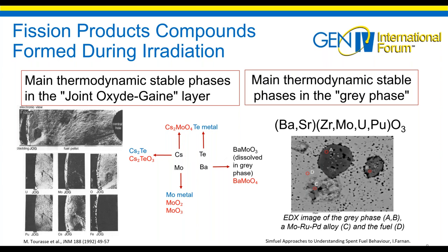And as we can see here, in this layer we don't have any uranium nor plutonium, but the main compounds are cesium, molybdenum, oxygen, and the most thermodynamically stable phase there is the Cs2MoO4. Another phase can be found in the irradiated fuel called the gray phase, which is barium and strontium combined with zirconium, molybdenum, uranium, plutonium, and oxygen. And these phases will be really understood during this presentation.